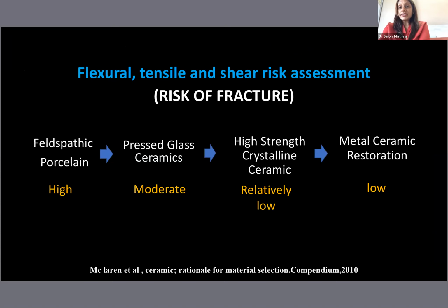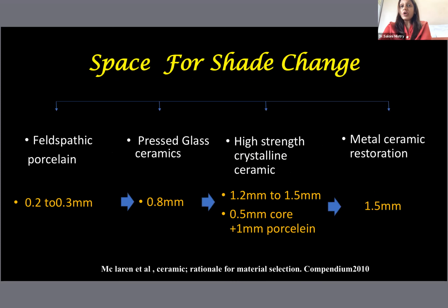In terms of flexural strength, we do understand the risk of fracture is higher in the case of feldspathic or pressed glass ceramics. But with zirconia, you have a lower risk of fracture, obviously. Even for the space that we require, lithium disilicate is obviously going to need more than zirconia. Zirconia in thinner sections can be done, but lithium disilicate requires somewhat thicker sections as compared to our PFM. PFMs are the least conservative of restorations, which are our gold standards.